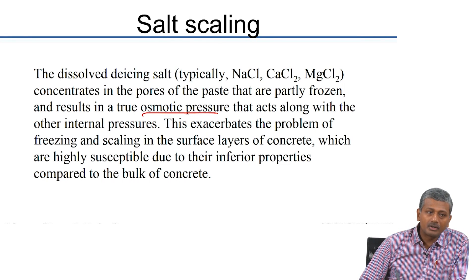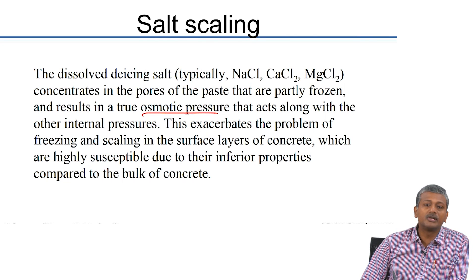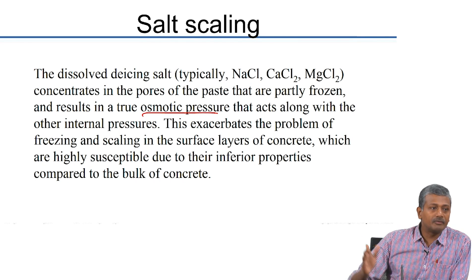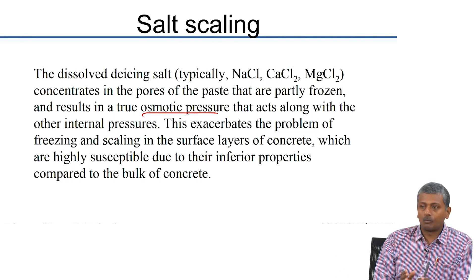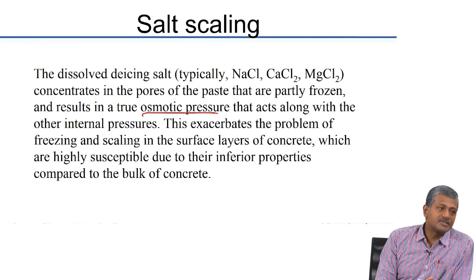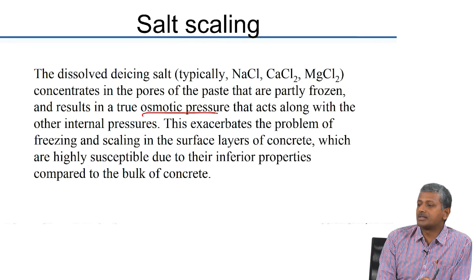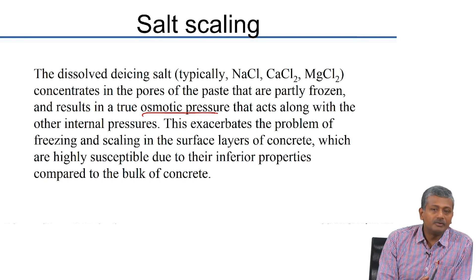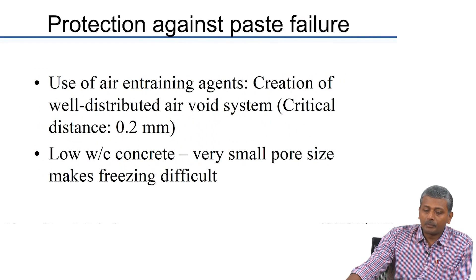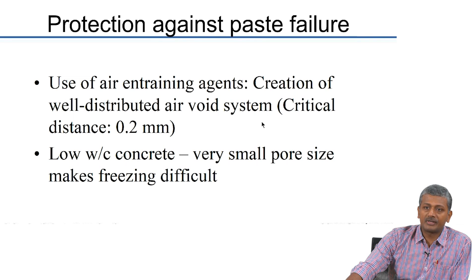When you are reducing water cement ratio, you are reducing porosity and your capillary pores become much finer — this further depresses the freezing point. So freezing inside concrete with very low water cement ratio will not happen easily. Lowering water cement ratio is a positive factor to improve resistance against freezing and thawing, and using high performance concrete will generally tend to improve concrete against freezing and thawing. Protection is offered by using air entraining agents and using very low water to cement ratio.